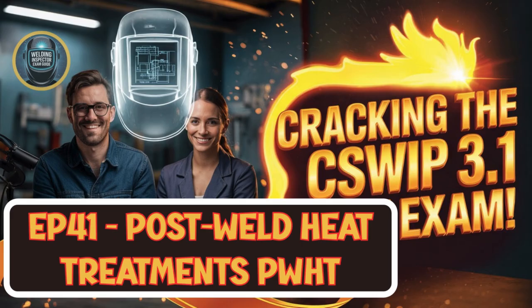Precisely. Then, they ensure the procedure itself is being followed exactly. Are they using the right method? Are the heating and cooling rates within the limits? Is the soak temperature correct? Is the soak time long enough? Are they measuring temperature correctly? And finally, they're responsible for making sure all the documentation is done properly. Charts, records, everything needs to be documented to prove the heat treatment was performed correctly according to the code or standard. It provides that traceable record. So it's a really hands-on oversight role.